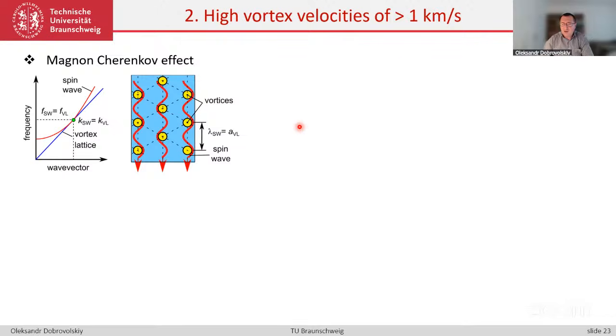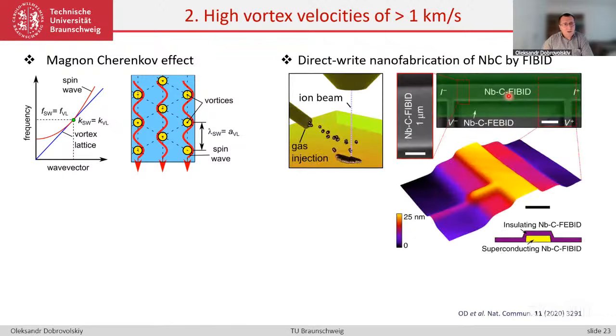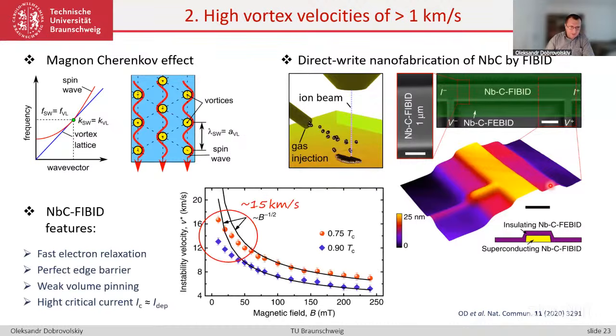And these materials were realized by direct writing under the action of focused ion beam induced deposition. It was possible to fabricate niobium carbide strips, which are characterized by close to perfect barriers for vortex entry. This material is additionally characterized by very short quasi-particle relaxation time, weak volume pinning, and high critical current. So in principle, it's possible to apply such currents, which accelerate vortices to very high velocities.